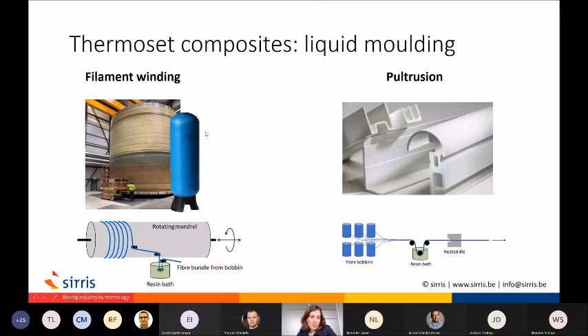Then two other liquid molding processes are filament winding. Here you see a tank that was developed quite recently. It has a diameter of 15 meters. It has more than 2,000 cubic meters of content. So this is a huge structure. This is made with filament winding. So you wind the fiber, which is already impregnated through a resin bath. But of course, there are also smaller tanks that are made with this kind of process. A variant is pultrusion, where you pull a fiber through a resin bath and impregnate it to make profiles like this.